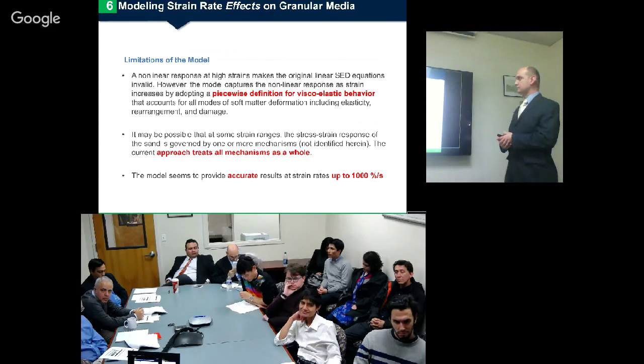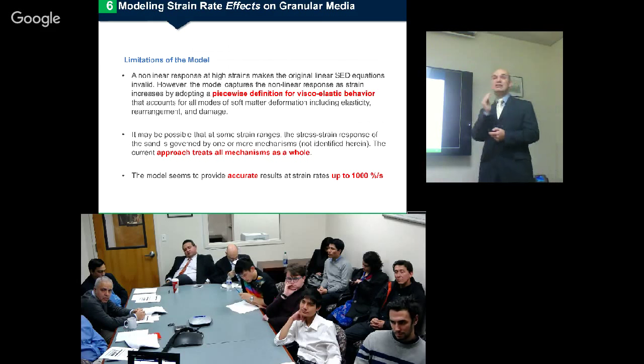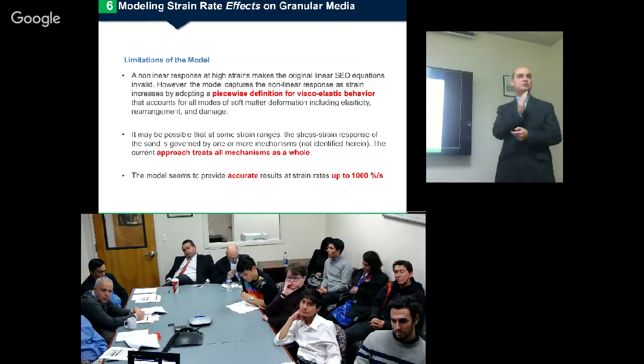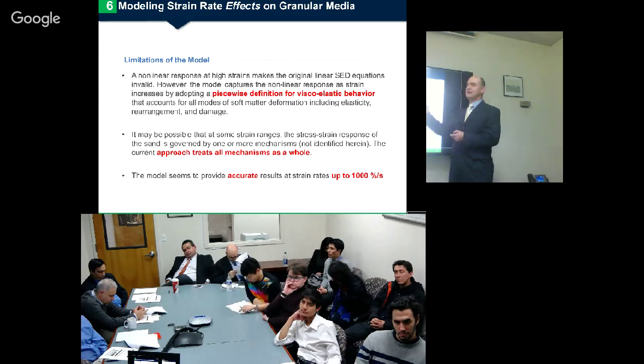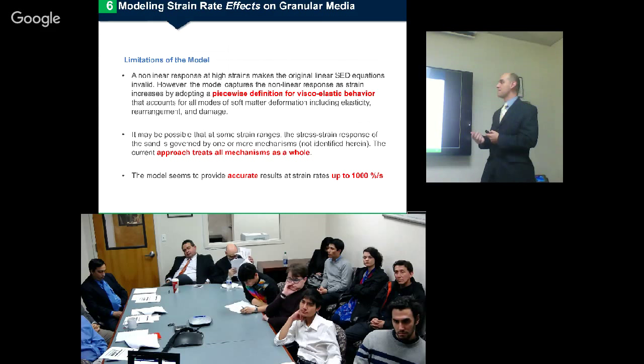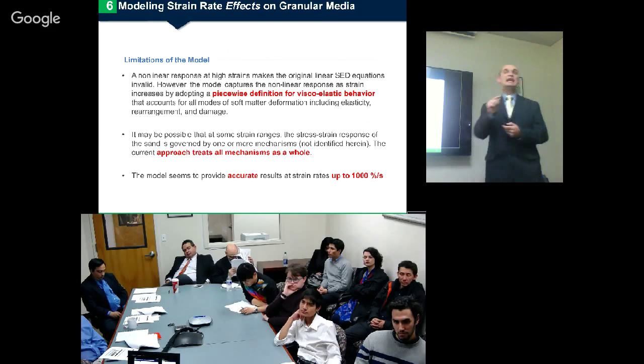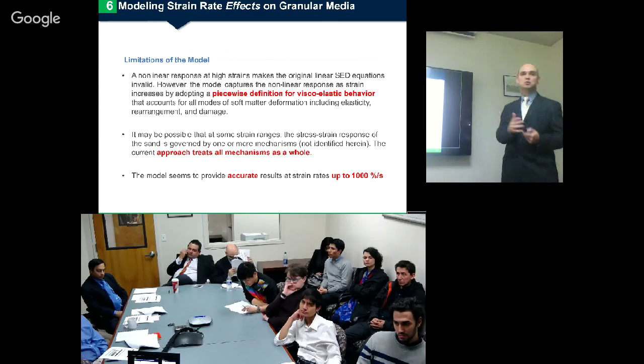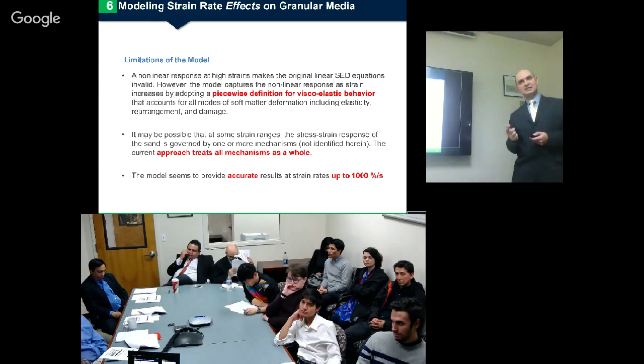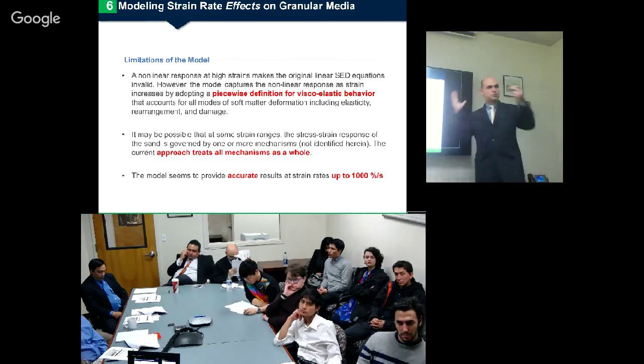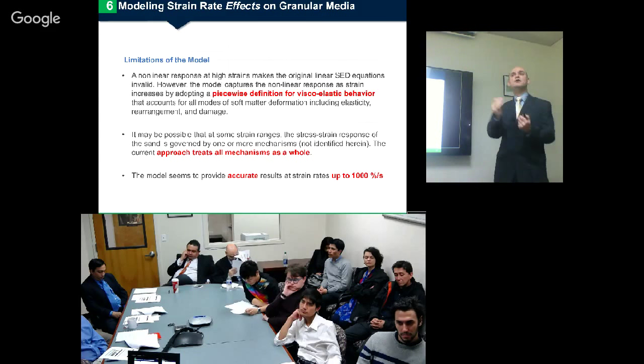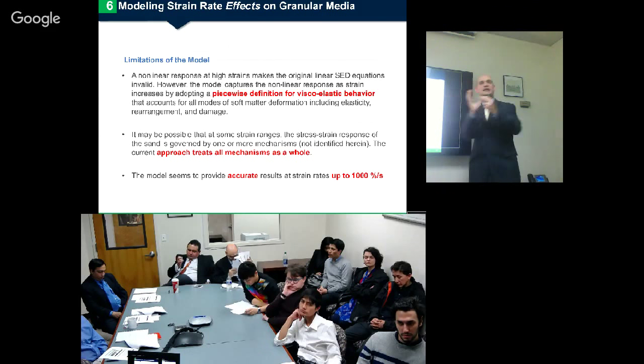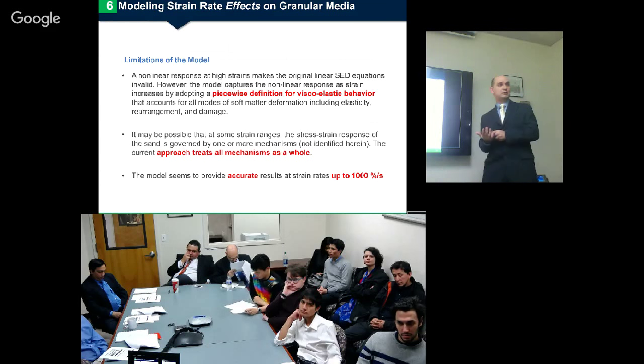So, a few limitations of the model. Obviously, the higher the strains we apply, the more invalid the model is going to be. However, the model captures a non-linear response as the strain rate increases by using a piecewise definition for viscoelastic behavior altogether. So the model captures or wraps different conditions within the entire experiment, such as elasticity, rearrangements, and particle damage of the behavior.